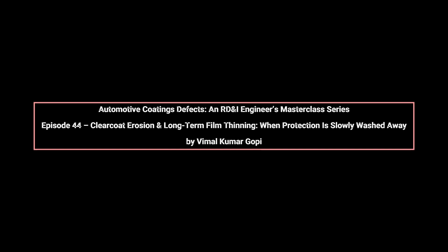OEM durability validation evaluates erosion indirectly through combined testing. UV exposure followed by wash simulation, humidity cycling, and mechanical abrasion tests are used to reproduce real-world thinning behavior. Thickness loss measurements and gloss retention trends provide insight into end-of-life appearance performance.